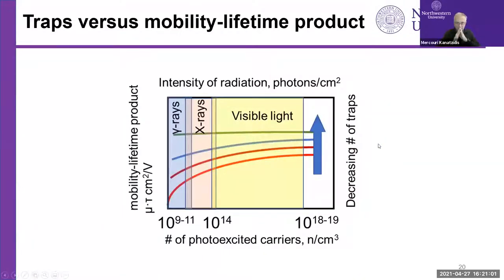So one thing to point out here is the mu tau is dependent on the number of photoexcited carriers. In terms of how many photons you have when you test for gamma rays versus X-rays versus visible light, it varies by orders of magnitude. In other words, gamma ray sources typically have 10 to the 9 to 10 to the 11 photons per square centimeter. X-rays have another three orders of magnitude more, and visible light has another two or three orders more photons.